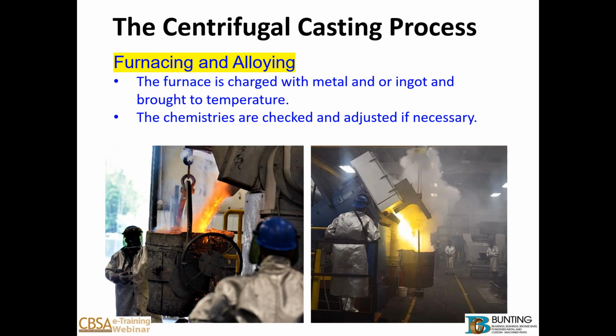Okay, so what we do first is we melt chips or ingot or a mixture of both in one of our induction furnaces, and then the metal is poured into a large ladle, which is then taken to the centrifugal caster. Once the metal has been poured in, any slag that is on the top is then skimmed off the top to leave the pure molten metal. So if you notice the picture on the left, we've got the ladle being poured into from the furnace. On the right, that's another view of a similar process. So the furnace, which is typically around 3,000 pound loading, will load into the ladle. And that defines the amount of weight that you can pour into the centrifugal. So that is one of the limiting factors when pouring a centrifugal, is how large your ladle is. And at this point, also the chemistry of the metal is checked to make sure it's within the CDA specification.